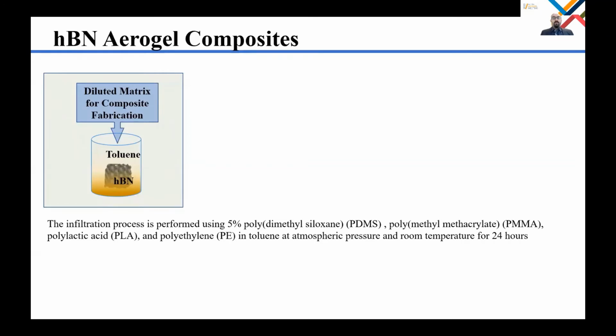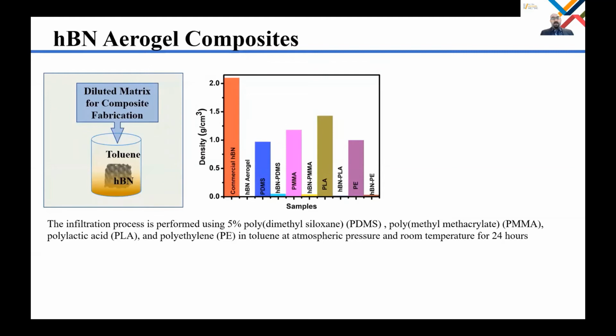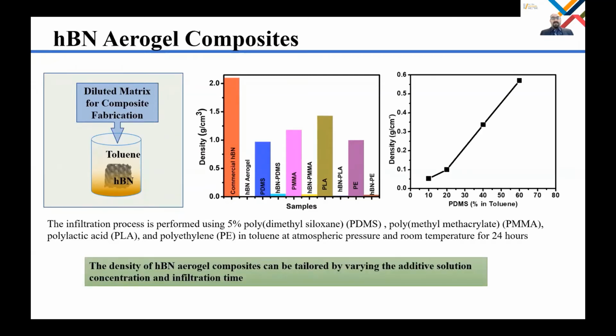Here we prepared the composite of BN aerogel by infiltration of polymer additives into the BN aerogel. We diluted PDMS, PMMA, polylactic acid, and polyethylene in toluene and immersed the BN aerogel into 5% polymer solution overnight. The density of BN polymer aerogels is much lower than bulk densities of the polymer and BN, as you see here. In addition, the density of the composite aerogel can be tuned by tuning the concentration of the polymer solution. Here we show as an example the BN PDMS aerogel. As you see here, the density of the BN PDMS aerogel increases with increasing concentration of PDMS solution.